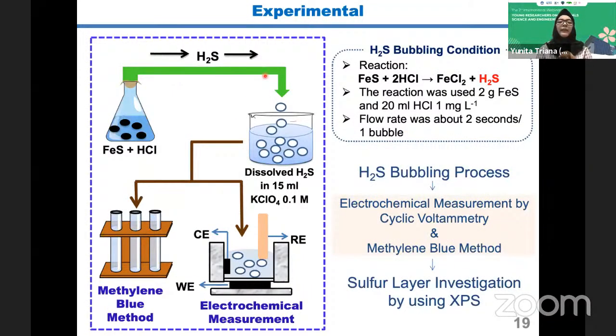And this is the simple experiment. I made hydrogen sulfide gas using a very simple reaction, FeS plus 2HCl, and it becomes H2S gas here. I bubble the gas from this tube into 0.1 molar KClO4. I detect the signal using electrochemical measurement, and the concentrations I check using the methylene blue method. So first is the H2S bubbling process, and then electrochemical measurement by cyclic voltammetry, with BDD as the working electrode, and also methylene blue to confirm the concentration. For the sulfur layer investigation, I used XPS to check the surface of the BDD.